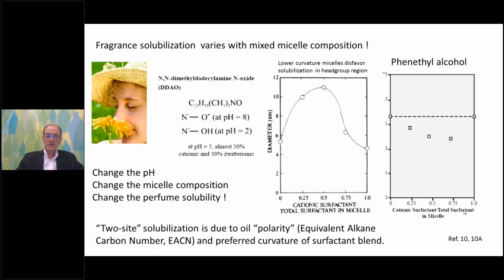And what we see is that the solubilization of the phenethyl alcohol goes through a minimum right around where the micelles are about 50% cationic. And we notice in the other plot that at that point, the micelle size is the largest. In other words, these micelles are rod-like, and the solubilization site of something that is polar, a polar oil like phenethyl alcohol, tends to be between the micelle head groups.